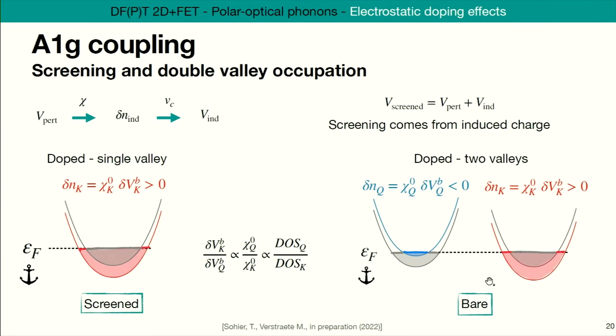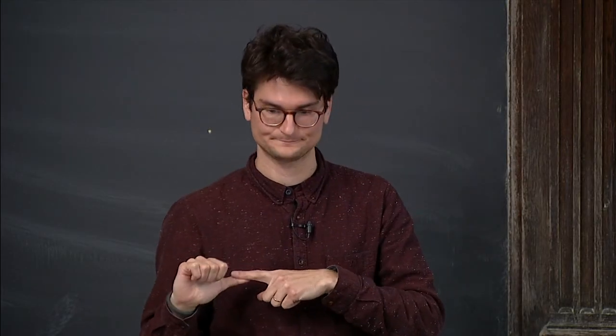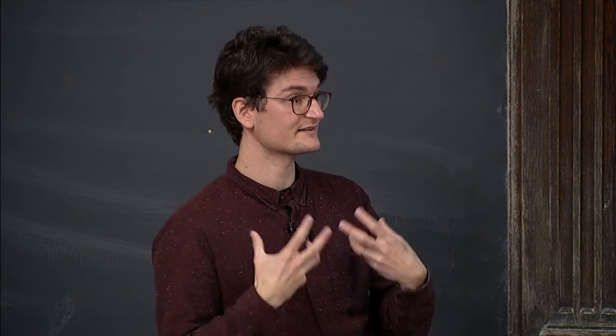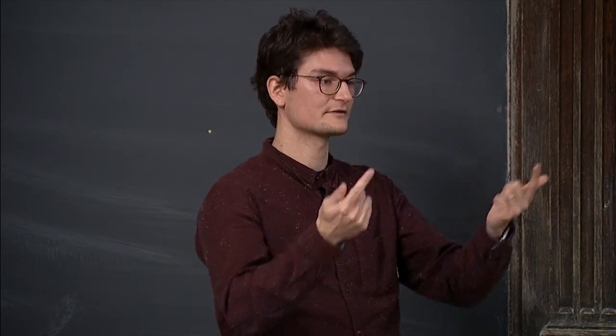Okay, now we can go back up the whole story. When we have two valleys occupied, there's no induced charge, no screening. The coupling is not screened. It stays bare. It stays strong. And so the phonons soften. And this is what we see in the experiment.